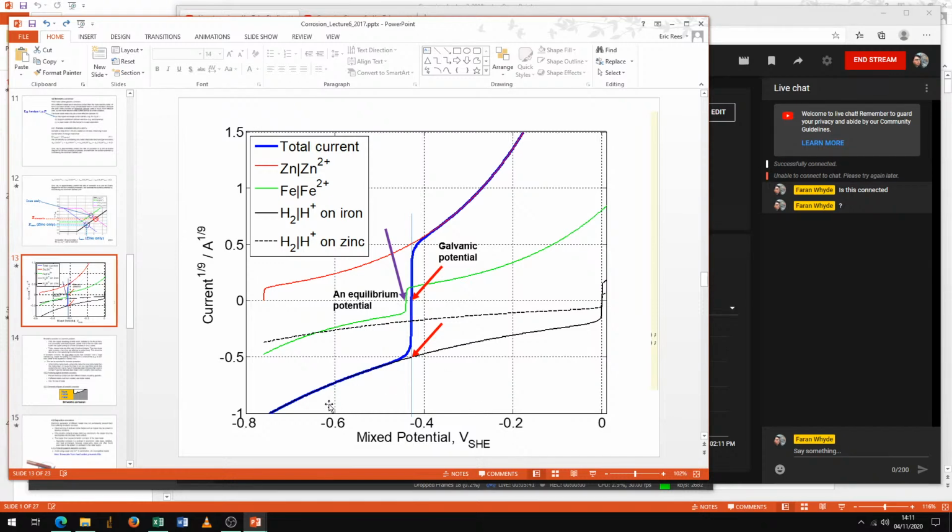You can do this by brute force because the equation is quite simple for each electrode. You just consider a few hundred different conceivable, plausible mixed surface potentials, volts against standard hydrogen electrode, and for each surface potential you compute the total amount of anode current for, say, zinc dissolving or iron dissolving, and the total amount of cathode current for, say, hydrogen evolution on zinc or hydrogen evolution on iron.